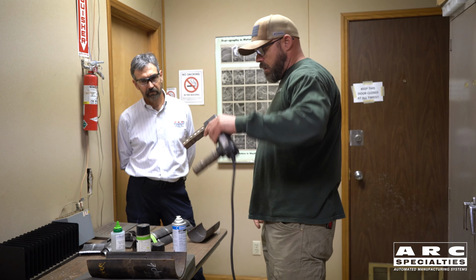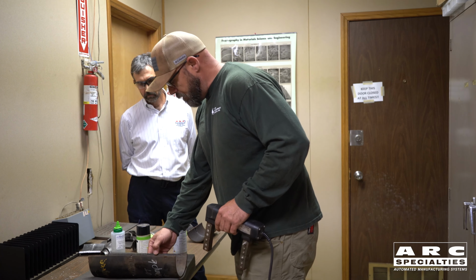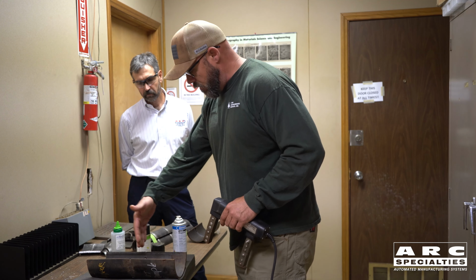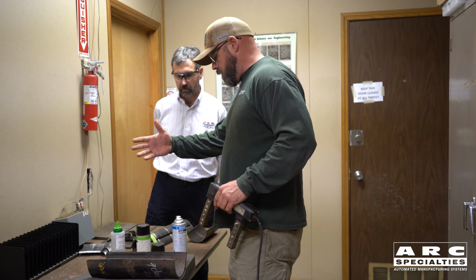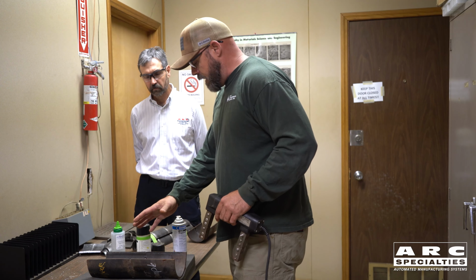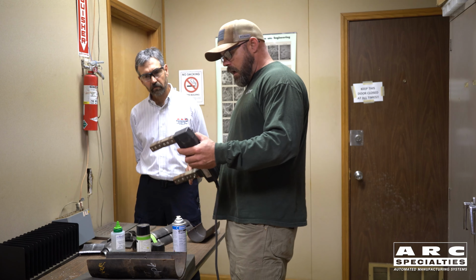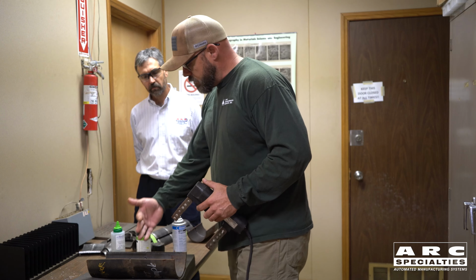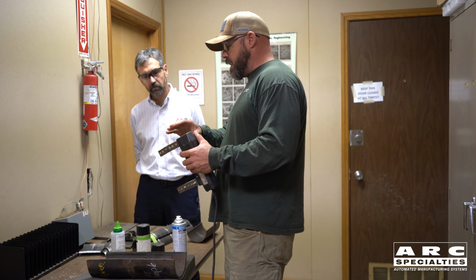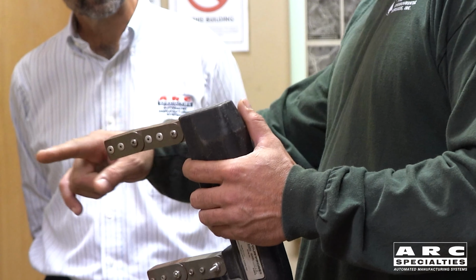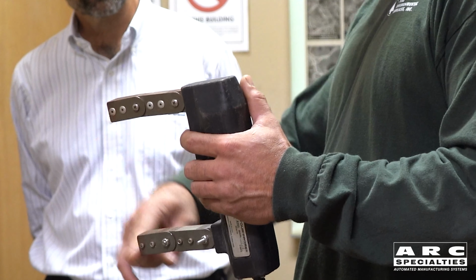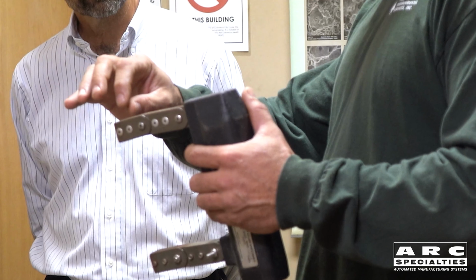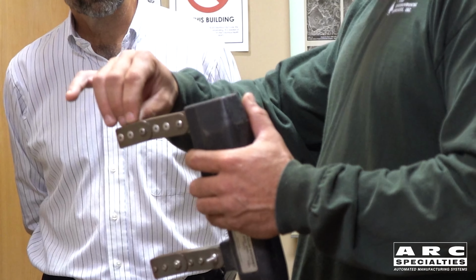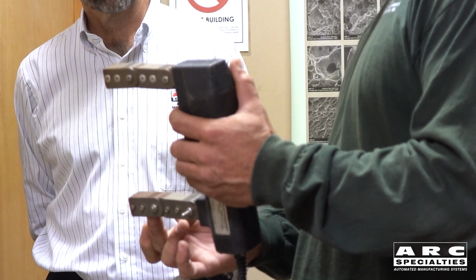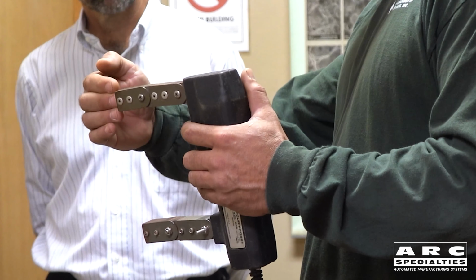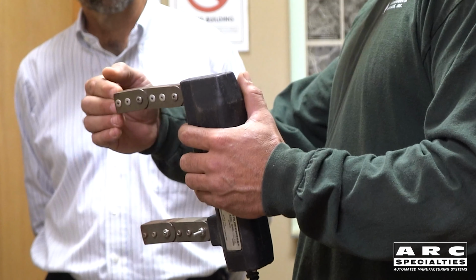How's it work? Well, the first thing you want to do is clean your part thoroughly. Wire brush, make sure you have no spatter, anything like that on the material. And then if you're looking for transverse cracks, the yoke makes a longitudinal field. So it's going to run from north to south or south to north, however it leaves the North Pole and it enters the South Pole.